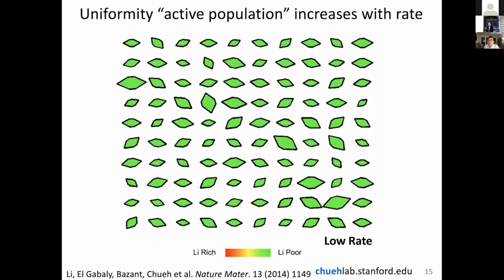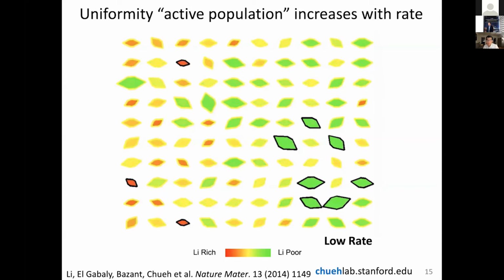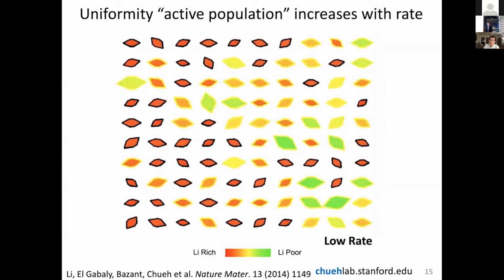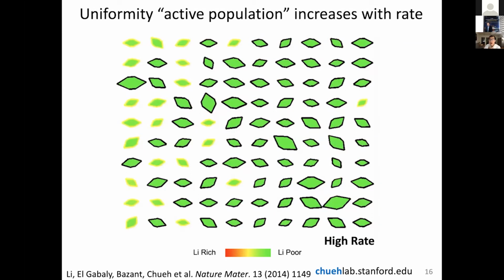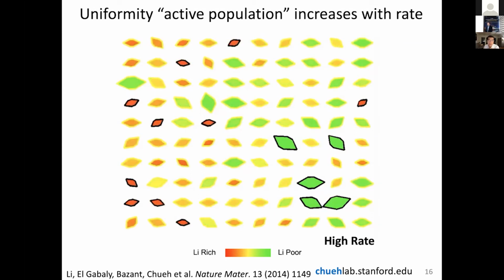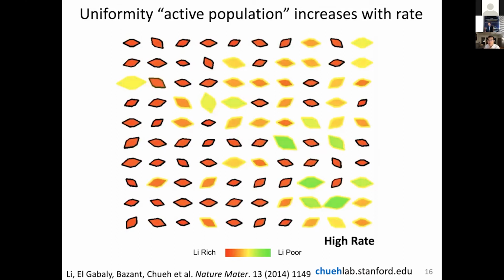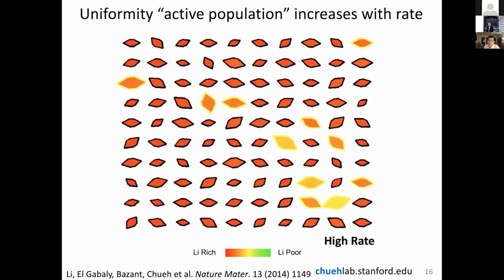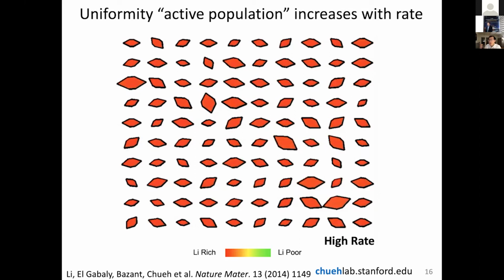So let me first show you a cartoon of what is happening. When you cycle lithium iron phosphate very slowly, say over tens of hours, you see this mosaic effect whereby very few % of the particles receive lithium. So this is very unexpected because thermodynamics tell you that when you approach a system very slowly, it should be very uniform, but it is not the case. On the other hand, when we go to very high rate, so this is now driving the system very quickly, maybe in half an hour or 15 minutes, then you actually see a much more uniform intercalation, which means that the active population actually increases with rate.